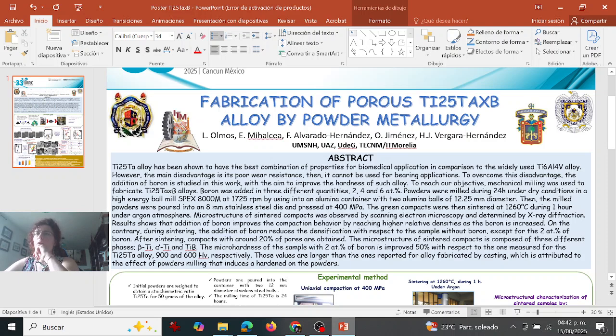Well, after that, the green compacts were then sintered at a temperature of 1260 degrees Celsius, and that during 1 hour and under an argon atmosphere. Well, the microstructures of the sintered compacts were observed by scanning electron microscopy and also determined by X-ray diffraction.